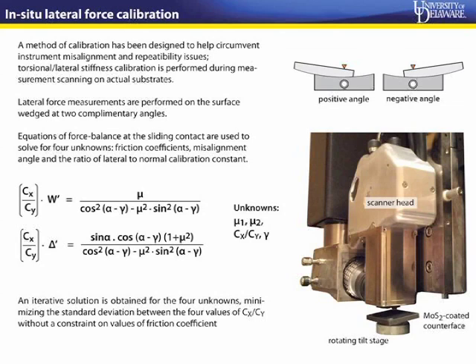Essentially, we'll make scans at different loads on a tilted substrate. Mu is of course unknown. Alpha is known from the normal signal trace of the AFM. And then we also introduce a misalignment angle gamma to account for the unknown misalignments within the instrument. These could be because of shear center offsets, transducer misalignments, photodiode misalignments, and so on. So this gamma seeks to account for those kinds of misalignments.